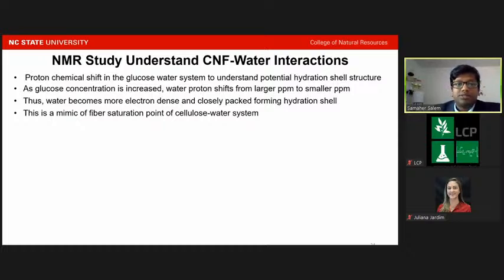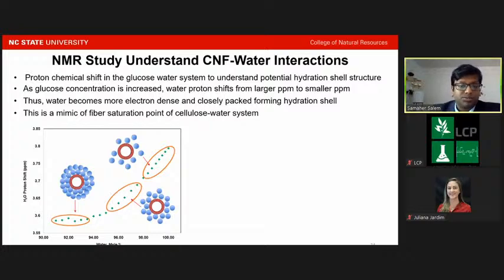As glucose concentration is increased, the water proton shifts from larger ppm to smaller ppm. Thus, water becomes more electron dense and closely packed, forming a hydration shell. This is a mimic of the fiber saturation point of the cellulose-water system.